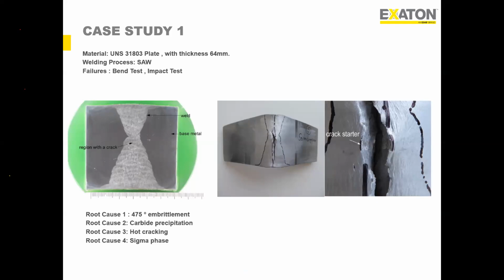This is probably one of the most challenging case studies I have seen, a real life problem. It happened at one of the top-notch shipbuilding companies. I'll not mention the name. They are in the top 5 shipbuilding companies in the world. So what happened? They were using 31803, which is a duplex material with a thickness of 64 millimeter, which is quite high. You can see the macro structures here. The process used was SAW. The failure was found during the bend test and impact testing.